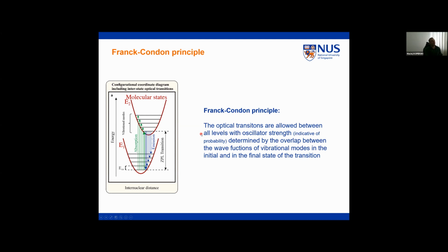And then what happens for a molecule when you shine light, you can elevate this electron to many different vibrational modes. At low temperature, you would see a relaxation to the ground vibrational state, and then you would observe emission to all of these vibrational modes coupled to the lower energy state. And all of these transitions usually merge and create these broad emission bands.